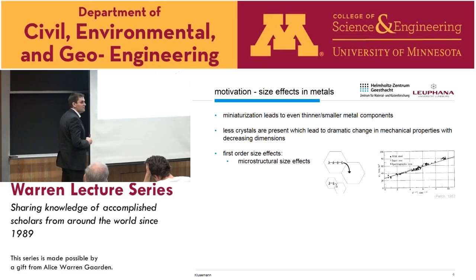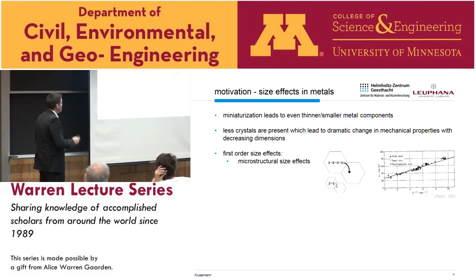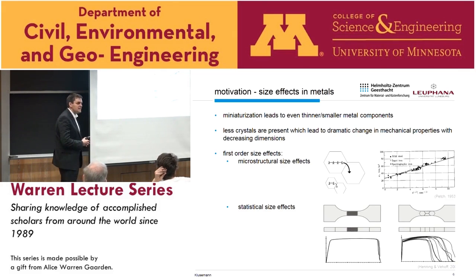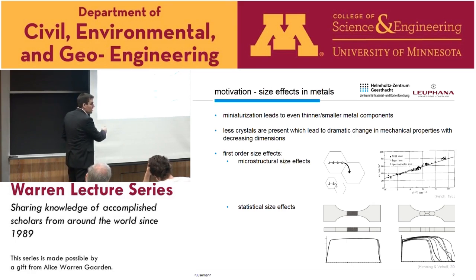So what I will talk about is first order size effects. As I mentioned, first order size effects are first of all the microstructure size effect, so classically Hall-Petch, which simply means the smaller my grain size gets, the stronger my material. It's related to the dislocations. What I'm talking about is the so-called statistical size effect, which is often forgotten, and that's just shown here. So you have your tensile specimen, and imagine the case you have a large number of grains here, and you have an isotropic orientation, isotropic texture, let's say. Then it actually doesn't matter what the single orientation of each of the grains is. You have always a kind of similar response if you do tensile tests on these kind of samples.